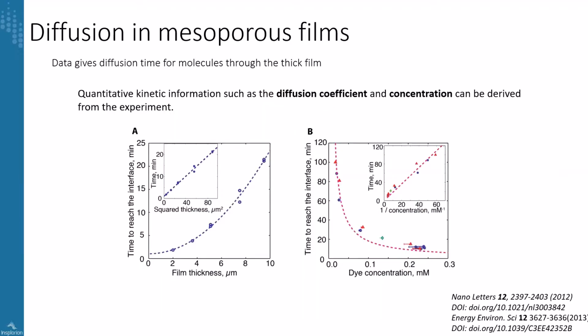Of course, the researchers kept going and studied a bit further, so they varied film thickness and they varied dye concentration, and with this information they were able to get quantitative kinetic data that allowed them to calculate the diffusion coefficient and the concentration that was being retained on the films during the experiments. So this is a great example on how to quantitatively use the NPS data, but also on how to explore the information that is available.